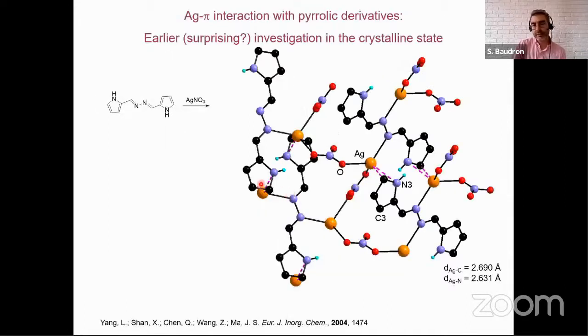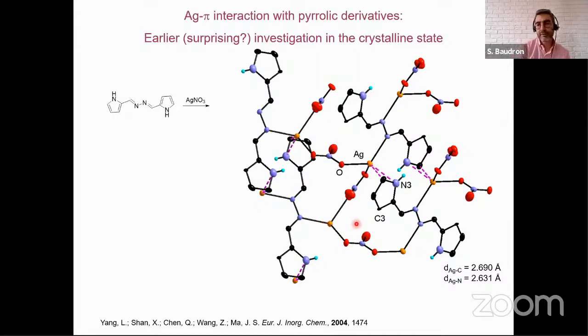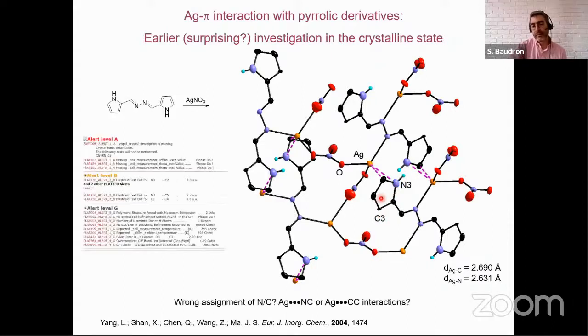And this struck us because if we come back to this original result that I showed you from the group of Ma, where they reported that the silver sits on top of a carbon-nitrogen bond, our results were at variance with this observation. So we started looking a bit closer at this crystal structure. And if we look at the ellipsoids of this structure, we do see that actually there is an odd organization of the nitrogen and the carbon in this case. And maybe this suggests that there has been a wrong assignment of a carbon to the nitrogen, and this would be indeed the carbon, and this atom would be the nitrogen, making it a carbon-carbon double bond interacting with a silver cation, which would be consistent with the result we have observed in our study.